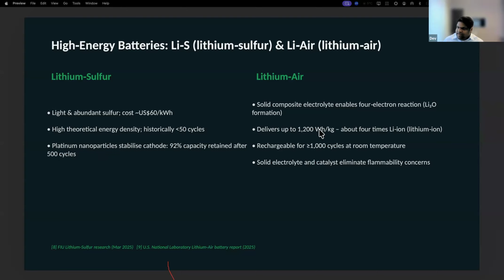Whereas the lithium air, if you look at it, a solid composite electrolyte enables four electron reactions, with dilithium oxide formation, and it delivers up to 1,200 watt hours per kilogram, much higher, about 4 times that of what we currently use in our electric vehicles. The rechargeable life is more than 1,000 cycles at room temperature, and the solid electrolyte and catalyst eliminate the flammability concern.